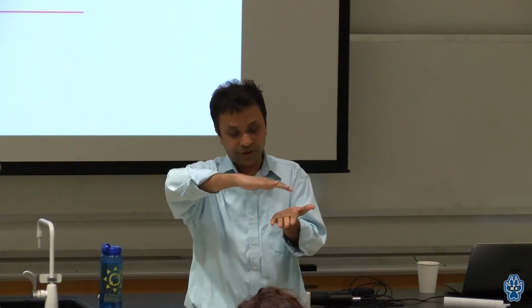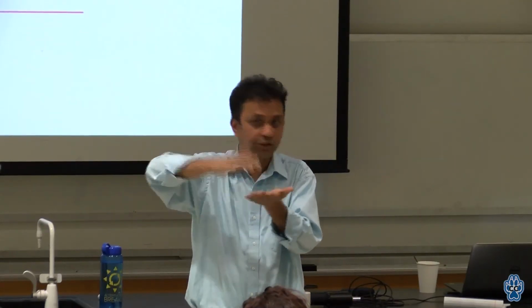Thank you for the fascinating talk and the idea of getting the Moiré effect through angle tuning and changing the properties that way. That's really remarkable. But one thing about materials like HOPG is that it doesn't conduct heat this way, it does conduct heat that way. I find that fascinating. When you twist the material or misalign the two layers, what happens to the conduction, which is usually along the plane? It doesn't conduct at all outside the plane, or the two stacks don't connect. People have studied two layers on top of each other, and there's no conduction this way, it's mostly conduction this way. But when you twist it, is there?